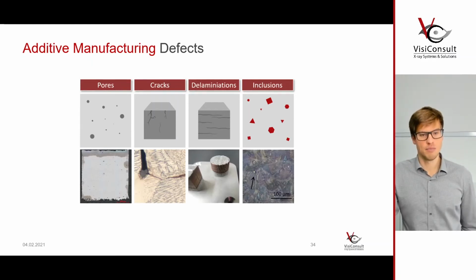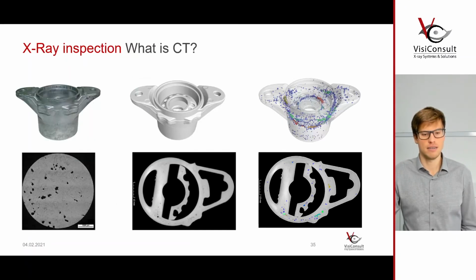And to make it even more complicated, most NDT methods are not working very well on additively manufactured parts. Ultrasonics, for example, is very hard on these complex structures. You have lattices, you have bionic features. It's very hard to do a proper UT scan on additive parts, if not impossible on most of them. Penetrant is critical, because you have a high surface roughness, so that means the whole part will be glowing. Penetrant is possible if you did a proper surface treatment, but for the whole internal passages, internal structures, and lattices, you can't use penetrant. So most specialists are of the opinion that probably CT is the best and most accurate inspection for additively manufactured parts.